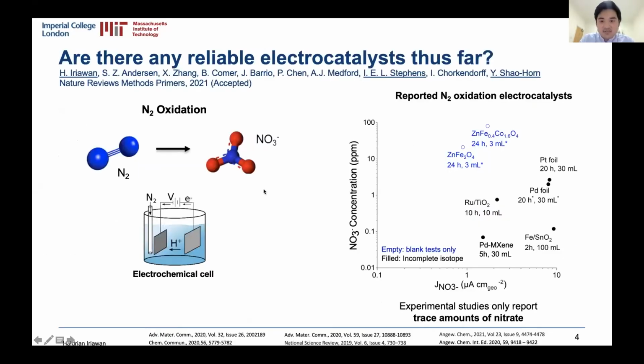Some proof of concept studies have been reported in literature reporting electrocatalysts to oxidize nitrogen. However, as we have plotted here, these studies report quite trace amounts of nitrate, the majority of them being around 10 parts per million or even much less than that. This essentially points to the inherent challenge of this reaction. Intuitively, this is because this nitrogen bond is really, really strong.